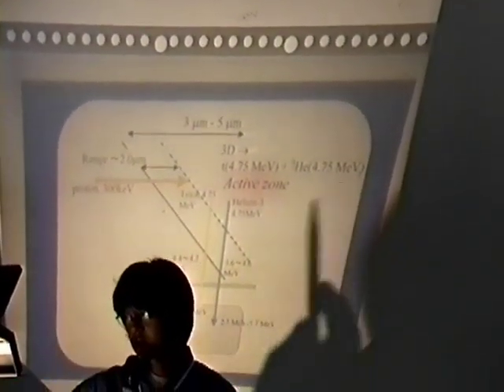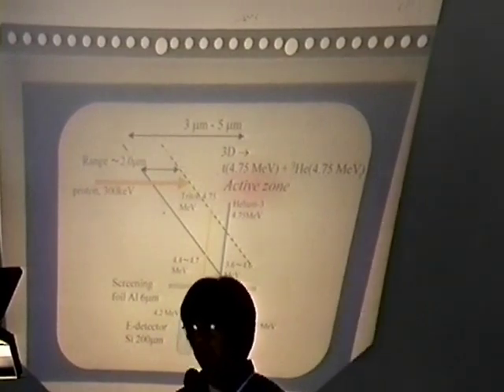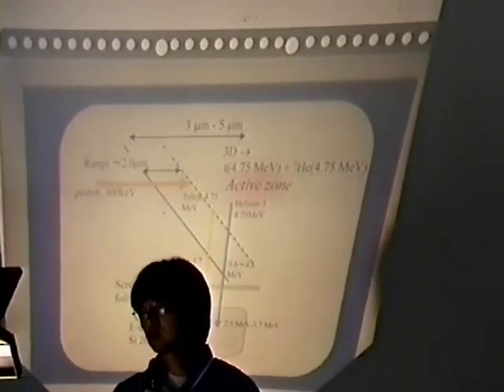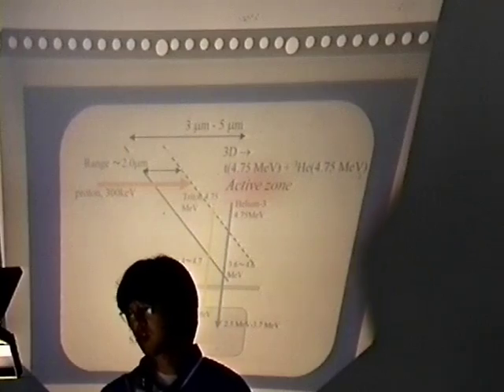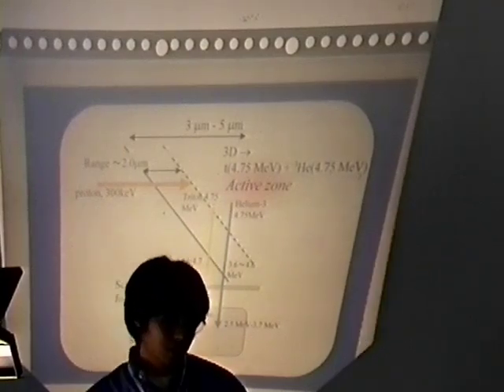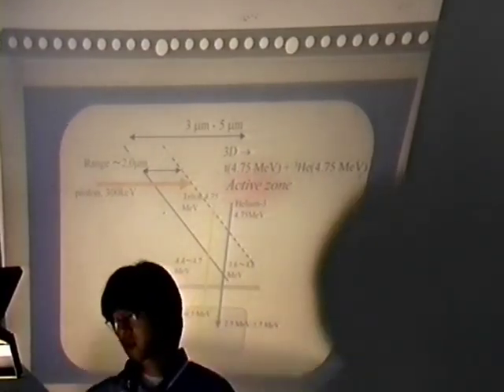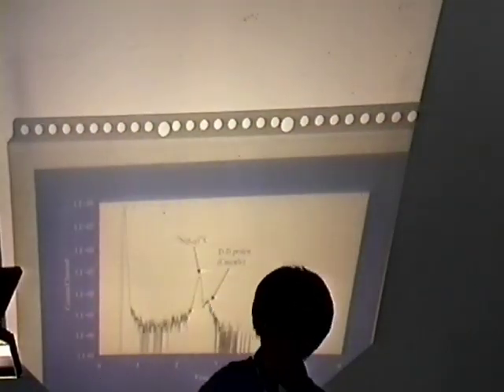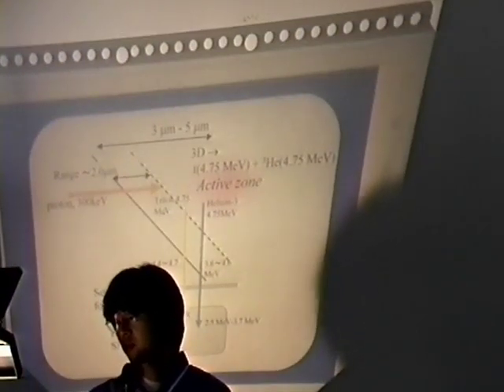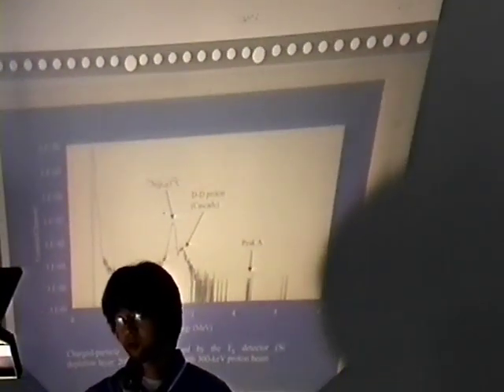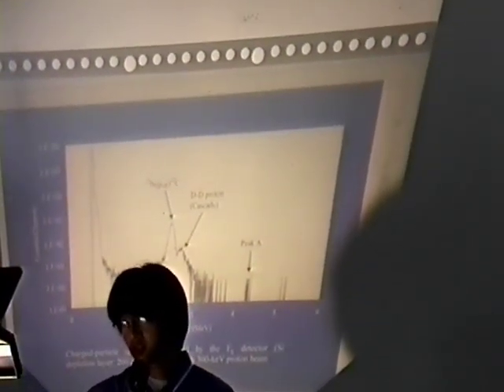This 3D reaction will take place in the deeper place in the target, and the emitted triton has about 4.3 MeV at the detector. This value agrees with this peak very well. And the partner particle, helium-3, has about 3.3 MeV at the detector, so the response of helium-3 may hide in this continuum.